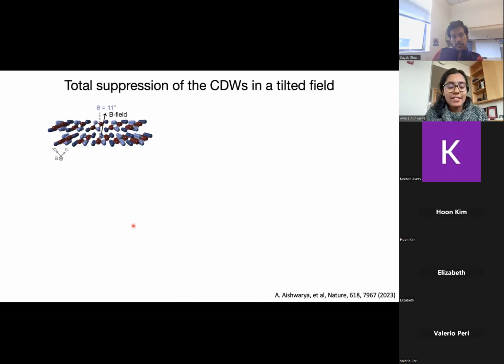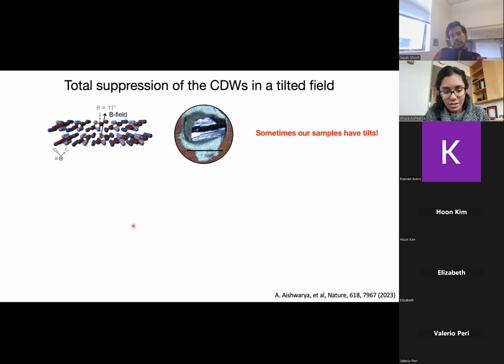Now, this material is very three-dimensional, and the way we glue it and cleave it to study in STM, we can sometimes have tilts, and this is not controllable at the moment. But it's interesting because UTe2 has a very anisotropic magnetic field dependence, so it can give us more information about the material.